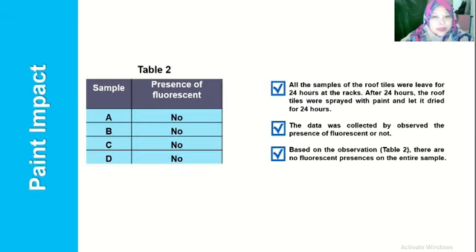Let's go to the paint impact test. All the samples of the roof tiles were left for 24 hours on the racks. After 24 hours, the roof tiles were sprayed with paint and left to dry for 24 hours. The data was collected by observing the presence of fluorescence or not. Based on the observation from table 2, there is no fluorescence present on any of the samples.